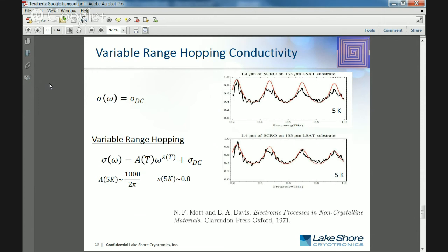And so we were able to apply some conductivity models to this, and the one that ended up working out well for us is variable range hopping. At low temperatures, the free carriers are really no longer free to move in the material. They're not responding to low frequency terahertz light, but respond well to the higher frequency. And looking at the material, what this is indicative of is a large number of defects, which lowers the conductivity and changes the material properties of these thin films.